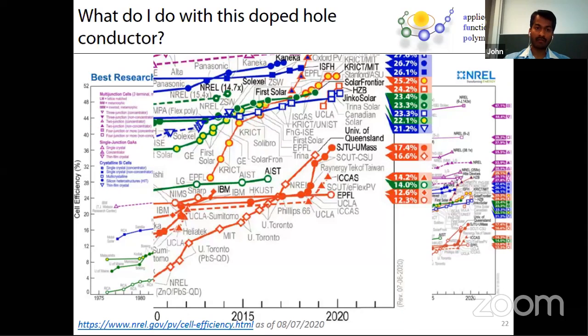So follow me through my laser pointer here. The yellow dots with red lines correspond to the perovskite solar cell devices, which I will explain in the next slide. This is actually very recent technology, which started around 2013, and then it went up to 25.2% efficiency in just less than 7 years. On the other hand, just right above here, this blue square, which is a 26.1 value, is nothing but the long-researched, quite conventional single crystalline silicon-based technology.